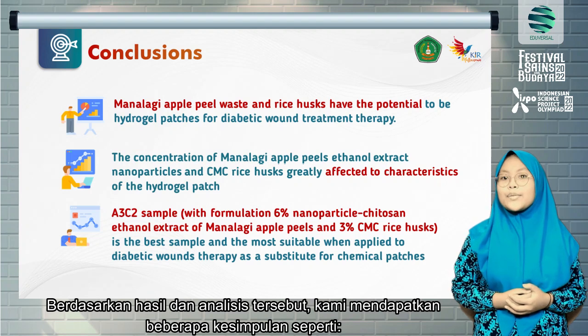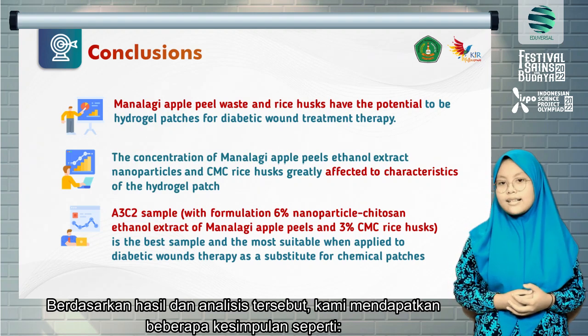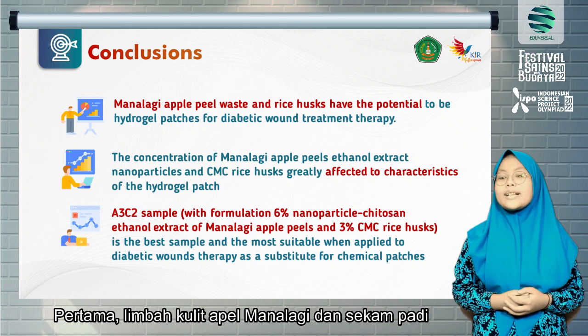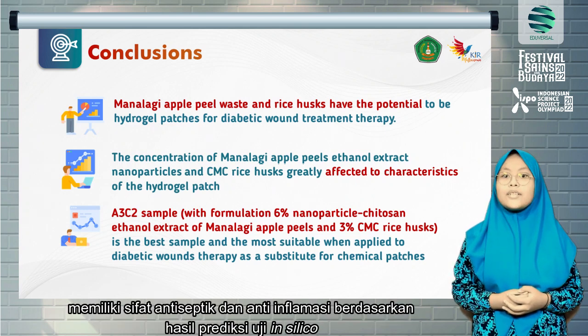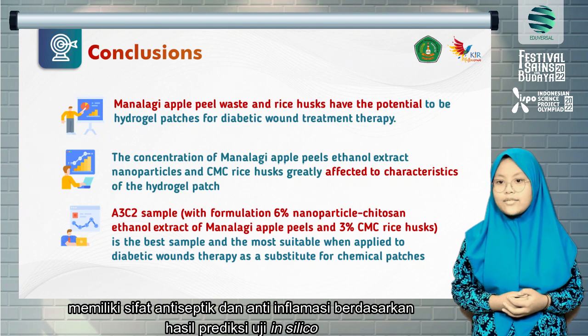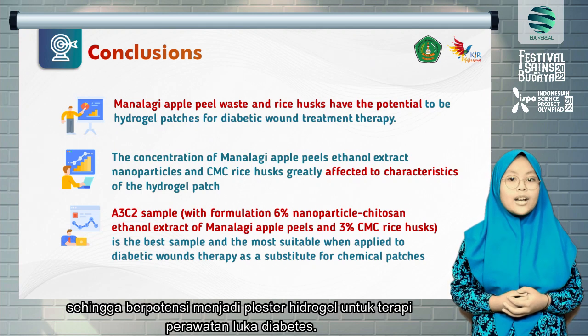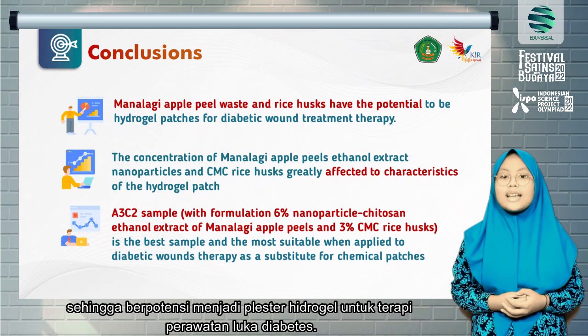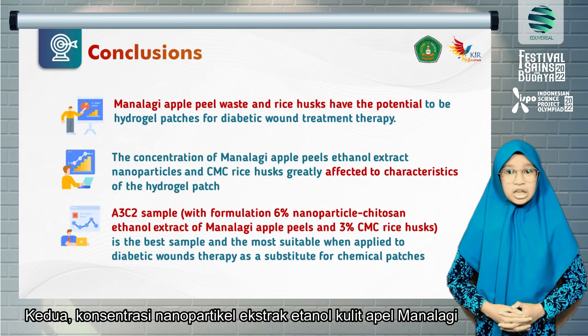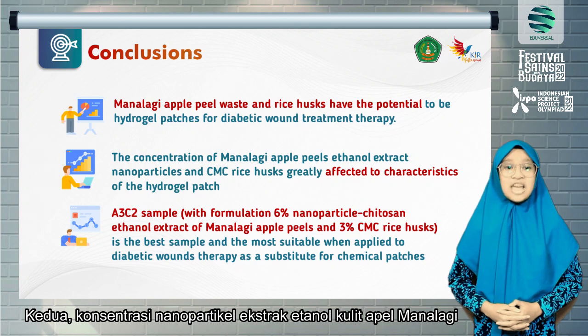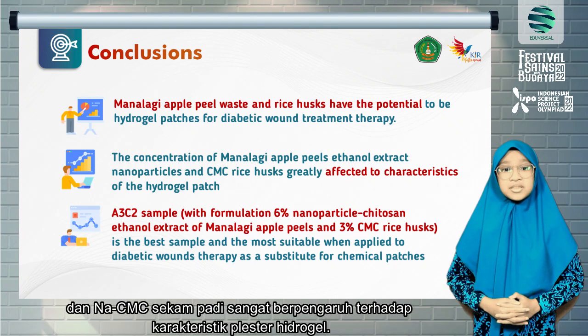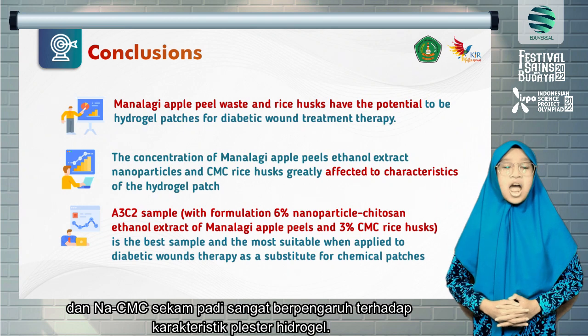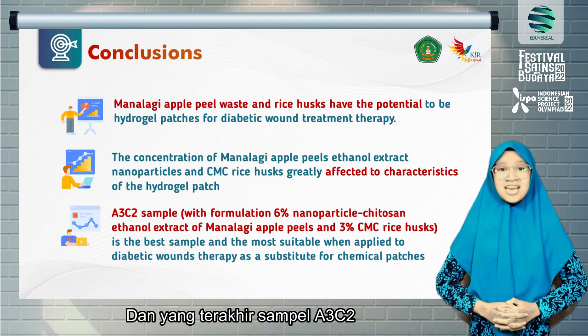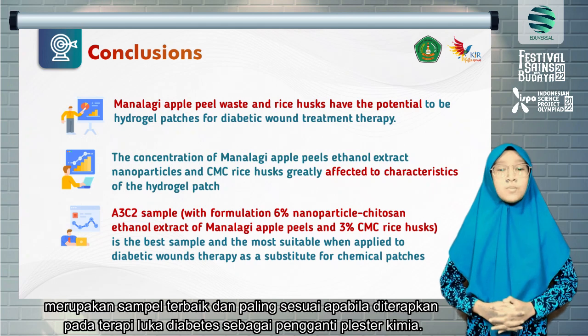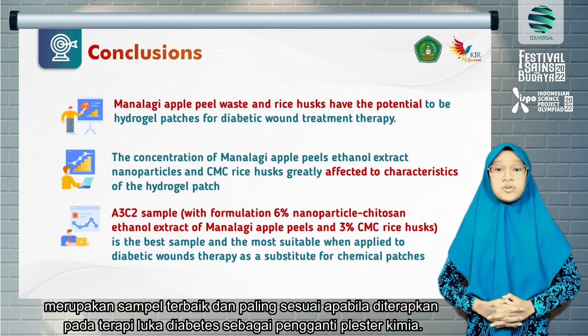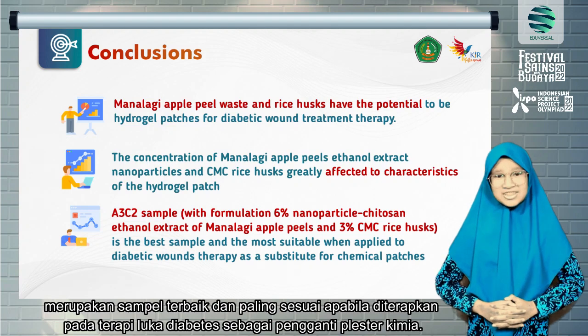Based on those results and analysis, we got some conclusions, such as first, manalagi apple peel waste and rice hulls have antiseptic and anti-inflammatory properties based on the prediction results of the in silico test, so that they have the potential to be hydrogel patches for diabetic wound treatment therapy. Second, the concentration of manalagi apple peel ethanol extract nanoparticles and CMC rice hulls greatly affected the characteristics of the hydrogel patch. And the last, the A3C2 sample is the best sample and the most suitable when applied to diabetic wound therapy as a substitute for chemical patches.